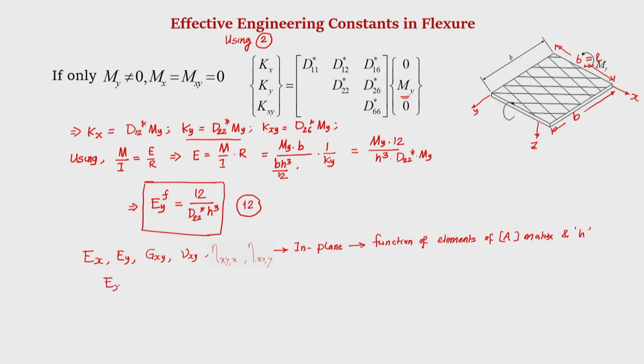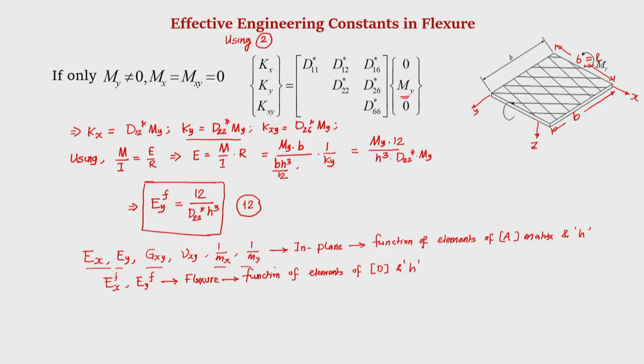We have also seen how we could determine the Young's modulus in flexure, okay, again as a function of elements of D and H. So, this gives us a first hand idea about the bending stiffness of the laminate, or the shear stiffness of the laminate, extensional stiffness of the laminate, or shear extension coupling. Okay. However, for a balanced symmetric laminate, the shear extension coupling will not be there, but for a general symmetric laminate, there may be shear extension coupling, and we could obtain the effective properties.